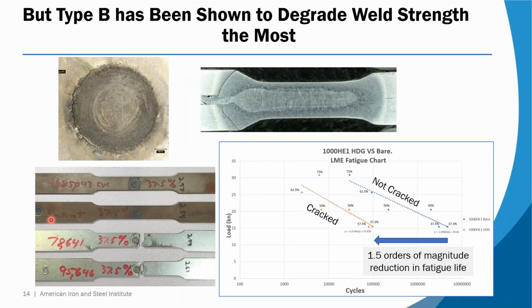Here we go, fatigue life. This is what I call flange tension. Each one of these samples is 2 tensile bars that were spot welded in the gauge section. There's a second piece underneath this one that you see, and we pull this, the width of a typical weld flange, like let's say a roof rail or something like that. If you did roof crush, you'd be putting the roof in this type of tensile load. So having this crack that you see here, oriented directly in the load path, has the greatest effect.